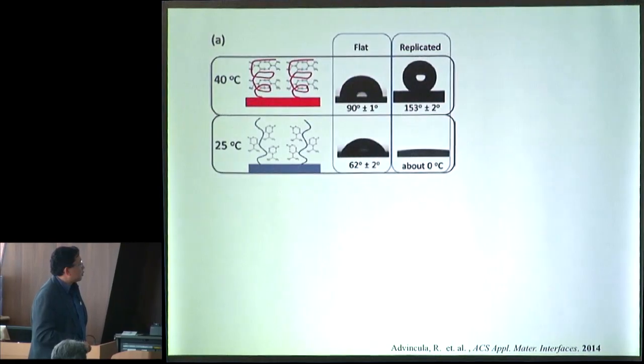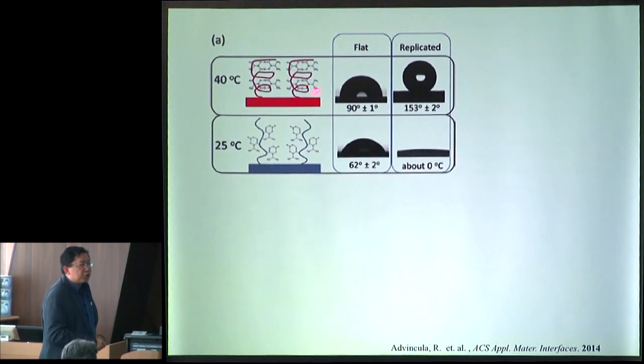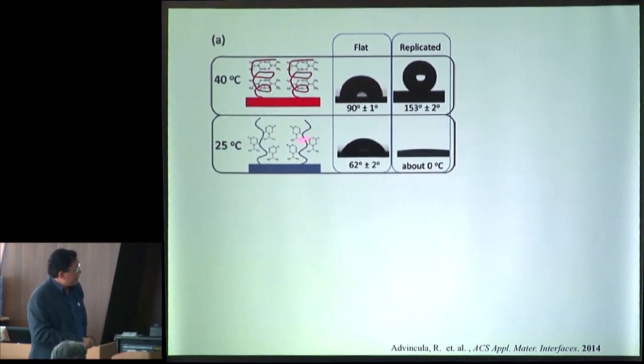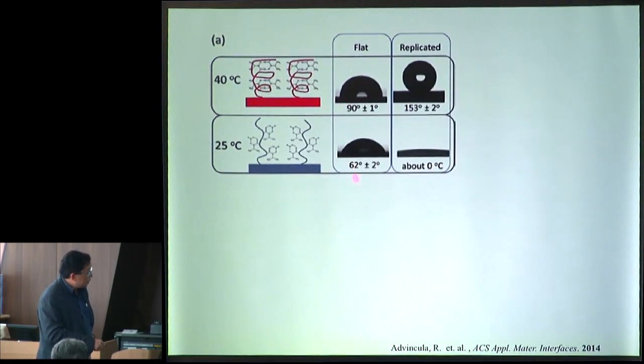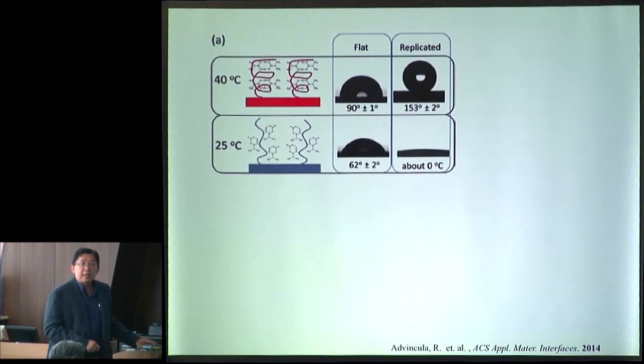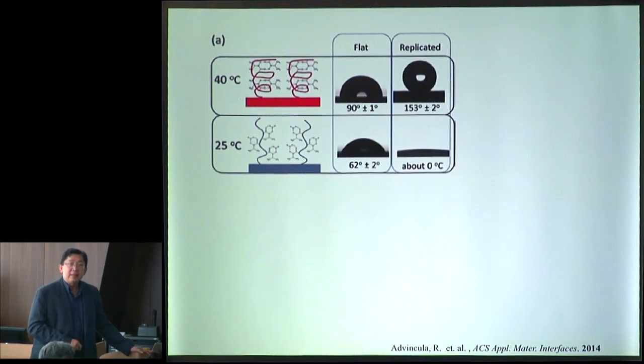Well, first of all, if we have a flat surface without a Lotus Leaf replica, okay, this is the behavior. The NIPAM has an LCST of 32 degrees C. So below 32, at 25, it's wetting, hydrophilic, not the best. But then heating it up to 40 degrees C converts it to hydrophobic, which you see by the increase in contact angle from 62 to 90.